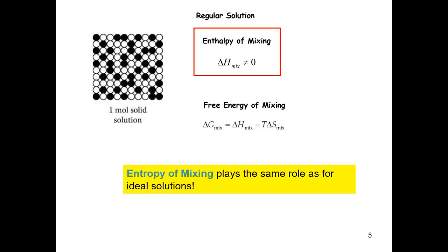This means that all of the possible configurations that you have for the ideal solution, you also have them here with equal probability. And we know that is not the case, because if you impose a non-zero interaction energy, not all of those configurations are going to be equally favorable, right? But for now, we do not distinguish that. We still consider that all of the configurations that contribute to the entropy of the ideal solution also play the same role here. So that is our first assumption, which makes this just a model for the real solution.